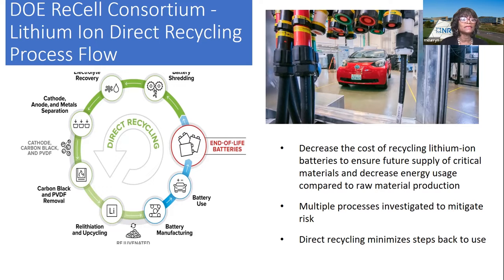Then there is the electrolyte recovery, which we do not participate in, but others do. We take that shredded material and do cathode, anode, and metals separation to form what is called a black mass. And with the black mass, we separate the cathode out, we separate the carbon black, and we're working to try to separate out the PVDF. Once we have the cathode separated out from the system, NREL does a relithiation process to upcycle the cathode, and once it's rejuvenated, it is put back into the battery manufacturing process, and then the battery is used and starts in the closed loop system once again. Next slide, please.